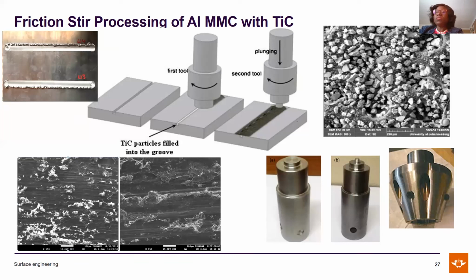And after that, we then plunge a second tool, designated as B in this case. We then use the tool with a pin to perform the friction stir processing. This particular study was aimed at improving the wear properties of aluminum alloy. We observed that because of the ceramic nature of TiC, it greatly improved the wear properties of the aluminum material in this particular study. Several other material characterizations were also conducted, but our main priority in this study is the wear study, and that is why I have shown you the 2 wear tracks that we got from this study.